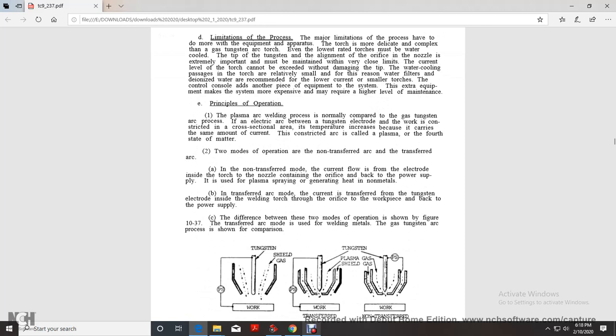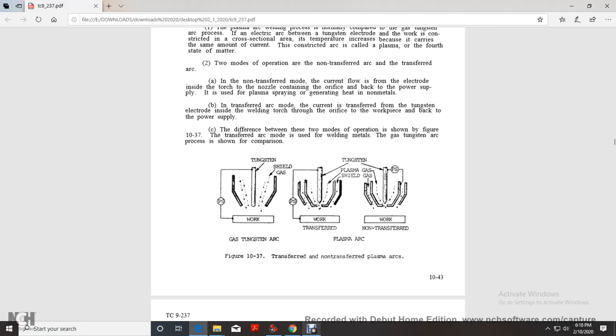In the non-transferred mode, the current flows from the electrode inside of the torch to the nozzle containing the orifice and back to the power supply, and is used for plasma spraying and generating heat in non-metals. In transferred arc mode, the current is transferred from the tungsten electrode inside of the welding torch through the orifice to the workpiece and back to the power supply. The difference between the two modes of operation is shown in Figure 10-37. The transferred arc mode is used for welding metal. The gas tungsten arc process is shown for comparison. It shows the gas tungsten arc welding, tungsten, shielding gas, work, and then the plasma arc, shielding gas, work, transferred and non-transferred.